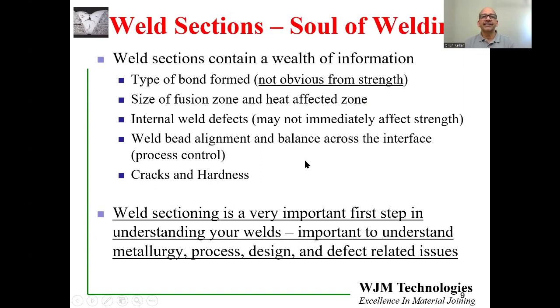The weld section analysis is the soul of welding. It provides a wealth of information. First of all, it tells you the type of bond which is formed, which is not obvious from the strength. A weld can be very, very strong and not have fusion. So this comes as a surprise to a lot of people. The size of the fusion zone and the heat affected zone is obvious from the weld section analysis. So we need to know what the size is, the size of the heat affected zone, which in many cases often decides the weld properties.